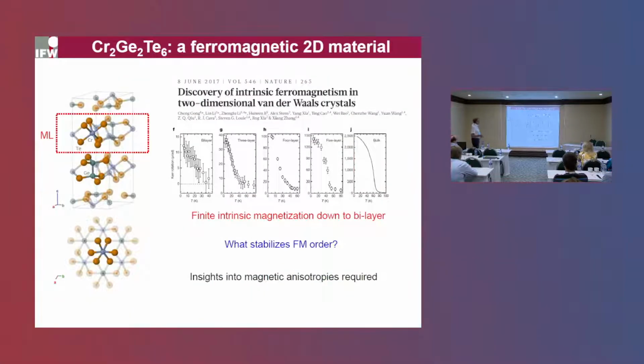So now let's come to this particular material, chromium germanium telluride. As with many other van der Waals systems, it presents a very typical structure. This is the chromium ion, six-fold coordinated by tellurium ligands, and they form a honeycomb lattice in the AB plane, and these honeycomb planes are stacked along the C direction, and they're coupled only very weakly by the van der Waals forces.